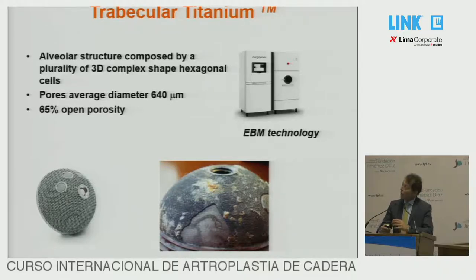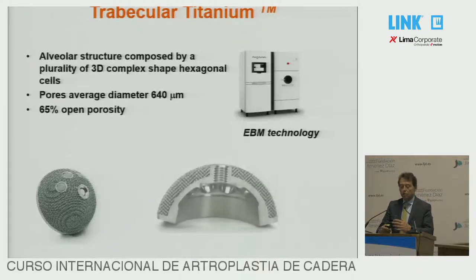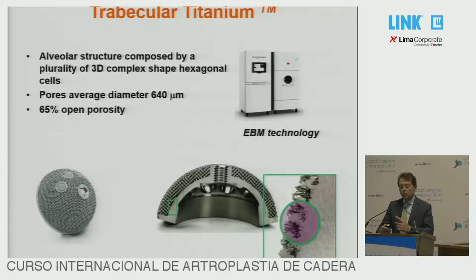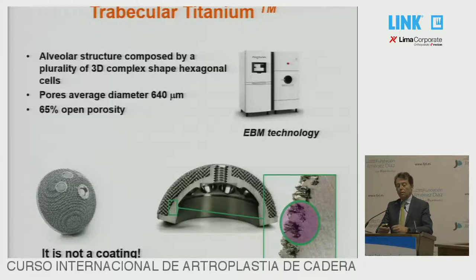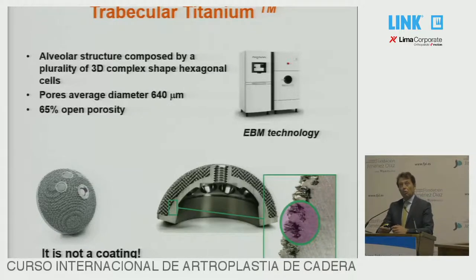65% open porosity — it's not a coating. The cap and the porous structure are a bulk structure. They are made with the EBM, electron beam melting technology — additive manufacturing.